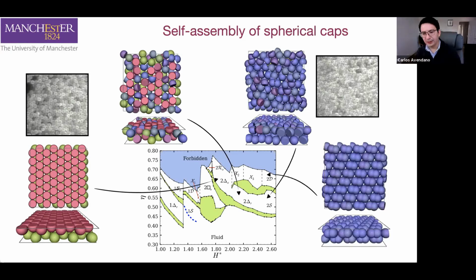And we observe again at higher densities that these particles tend to form dimers again, which will form more complex crystals. So you can see how by doing a small change in the particle shape, going from a sphere to something in which we remove a small section, was enough to make this phase diagram extremely complex. But this has an advantage because you can create crystals that do not have spherical symmetry. And for applications such as photonics, that's an advantage.